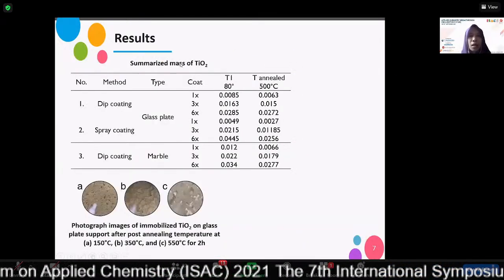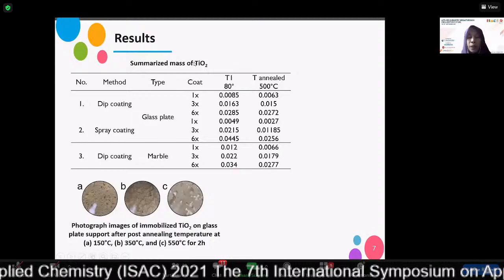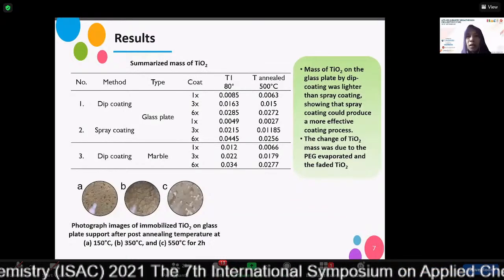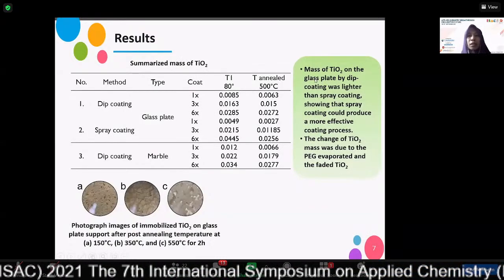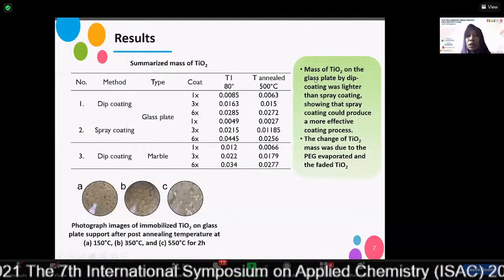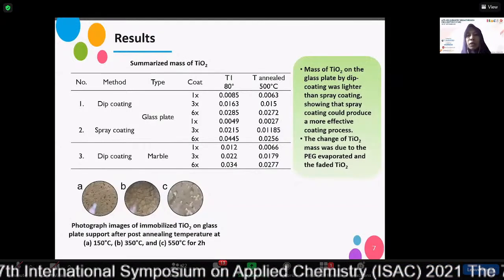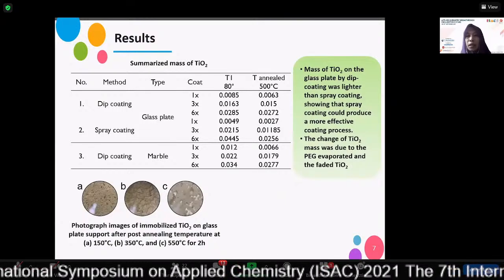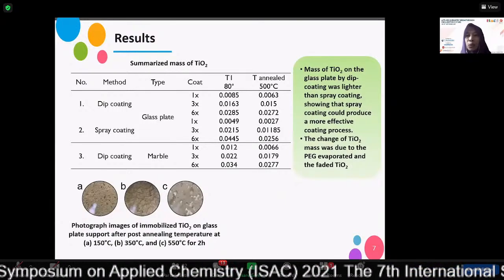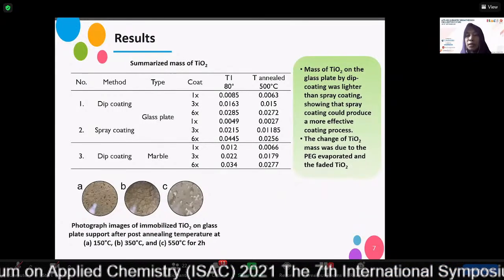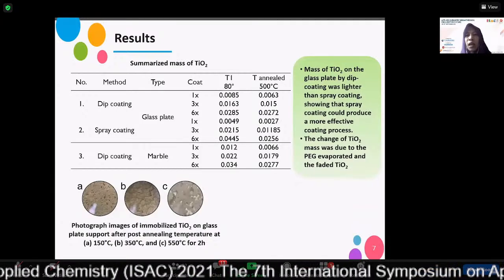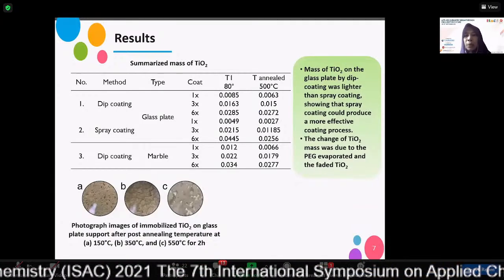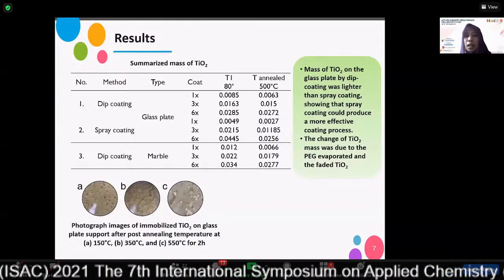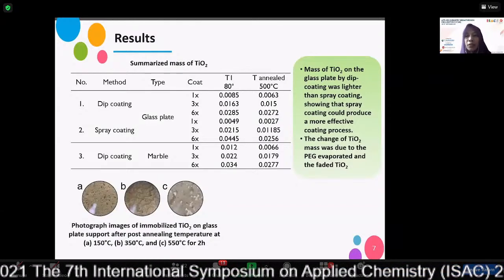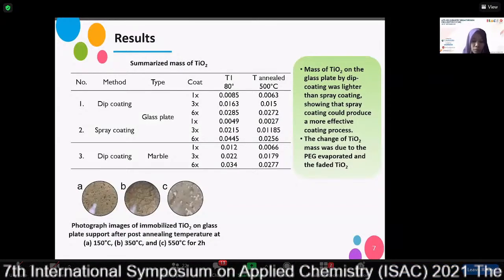This is the summarized mass of the prepared TiO2 coat. The results show that the mass of TiO2 on the glass plate by dip coating was lighter than spray coating, showing that the spray coating could produce a more effective coating process. And the change of TiO2 mass was due to the PEG evaporated and the faded TiO2.